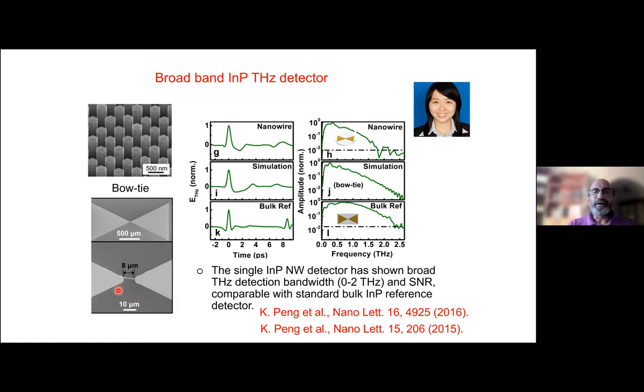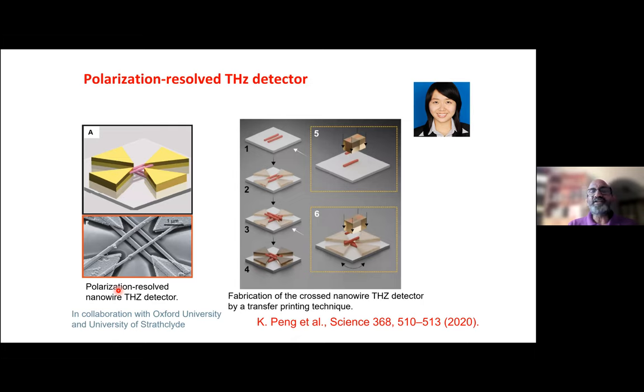During her postdoc at Oxford University, she has been developing these polarization resolved terahertz detectors. Instead of having only these bow-tie antennas with a single nanowire, we try to put another nanowire set at 90 degrees to the original one, so that you can measure both X and Y polarization, for example. The challenge has been to avoid physical contact between the top nanowires and the bottom nanowires. Again, this is working with my colleagues at the University of Strathclyde and Oxford as well. You can see that she was able to fabricate these structures after 3 years of hard work, working with electron beam lithography plus the nanoscale transfer printing technique with my colleagues at Strathclyde University.